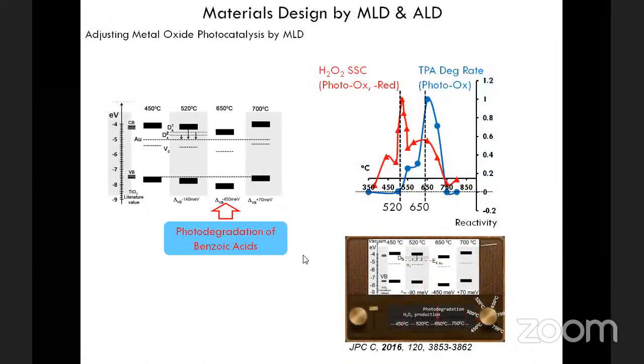And then the question came, what makes these unique reactivities? When we anneal at 650, how come it becomes this super photocatalyst for oxidative decomposition of organics here? And when we anneal it at 520, why do we get this unique photocatalytic reactivity towards hydrogen peroxide production? So what is special about these anneal conditions, and what is special about the material that we obtain? Simple elemental analysis showed that it has some carbon impurities. However, this oxide is not carbon-doped titanium dioxide, and this was very interesting.